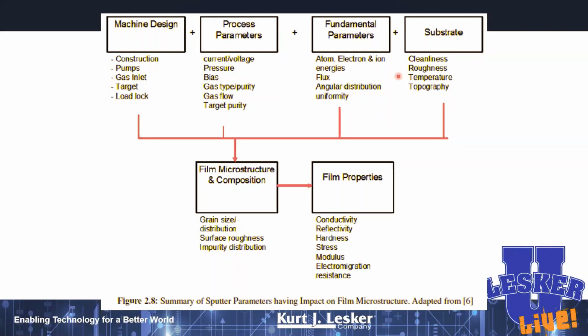I ranted a little bit about substrates. Again, I don't think people spend near enough time preparing their substrates. They have to be clean, pristine, never been touched by human hands. Even if they're super clean, you still got to be mindful of any surface defects, because surface texture, defects in your substrates, inclusions, things like that are going to affect how your films are going to grow. We may want to temperature control them, either heat them or cool them, in order to affect the morphology of your film.